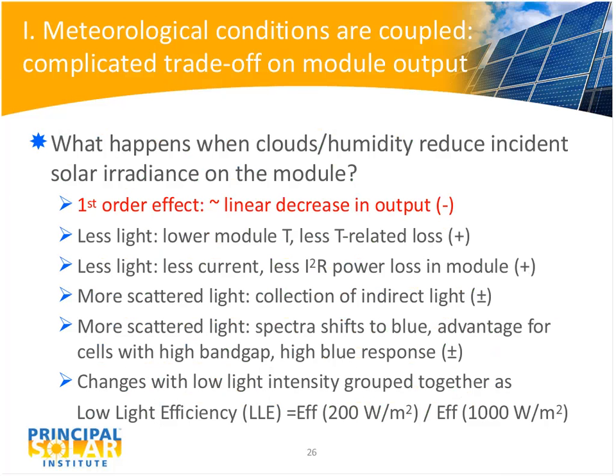So what happens when clouds or humidity reduce the incident sunlight on a module? Well, of course, the output goes down, like I said, linearly. But other things happen. For example, you have less light on the module, so it's going to be cooler, and therefore you'll have less temperature-related losses. With less light, you have less current, so you're going to have less I²R power losses. Haze and clouds give you more scattered light, more indirect light, and that could either add or subtract to your module efficiency, depending on how it's designed. More scattered light means the spectrum shifts to the blue, which is an advantage for cells that have higher band gap, or let's say higher blue response.